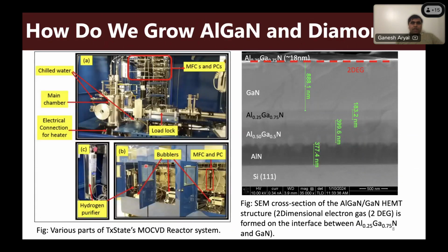So the question is, how do we grow aluminum gallium nitride or diamond in our lab? We use a metal organic chemical vapor deposition system to grow aluminum nitride or group III nitride materials. This image shows the various parts of the MOCVD reactor system that is available in our lab. Usually MOCVD works at a very high temperature, and we have to use a lot of gases like hydrogen, nitrogen, and ammonia, as well as precursors like trimethyl aluminum or trimethyl gallium. I will talk a little bit more about it on the next slide.